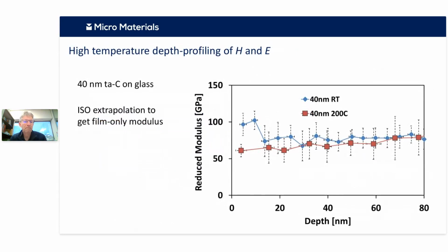So one thing that we haven't really talked about so far is how to do mechanical properties of coated systems as a function of depth. So this is also possible at high temperature if you have a thermally stable system where you've minimized your heat flow. And here you can see an example on a very thin amorphous carbon coating, which is slightly harder and stiffer than the glass substrate at room temperature, but as you can see here, as it's heating up, its near surface properties have degraded somewhat.